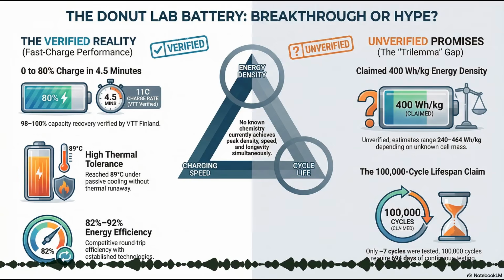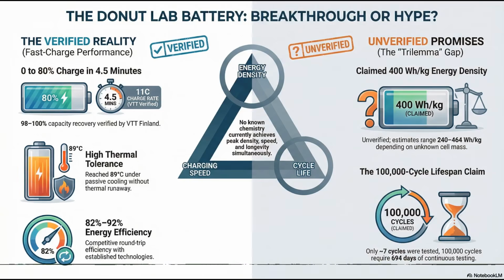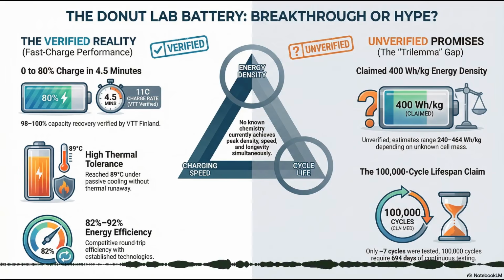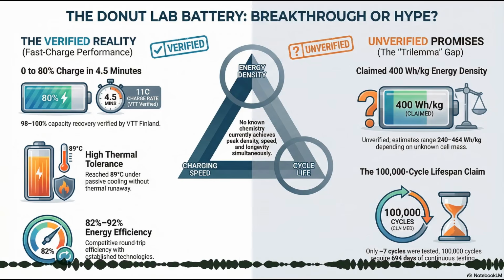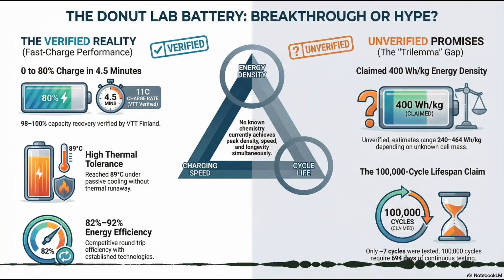It depends entirely on the chemistry you assume is inside. Let's look at the options. Scenario A, a polymer or composite electrolyte. These are basically functionalized plastics like PEO or similar matrices. They are very light. Density is usually around 1.2 to 1.6 grams per cubic centimeter. So if it's a polymer... If it's a polymer, the whole cell would likely weigh around 190 grams, and the energy density would actually be higher than their 400 claim. It might be hitting 460 Wh/kg. Wow, okay, so a polymer chemistry easily fits the physical math.